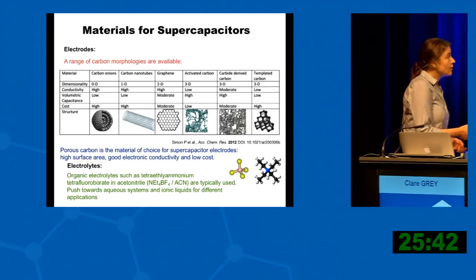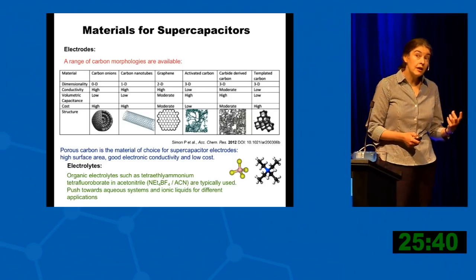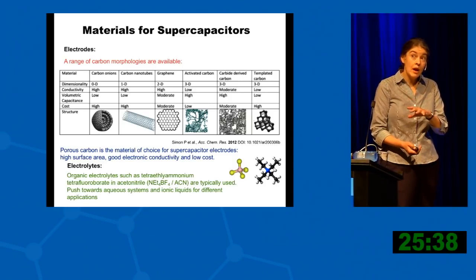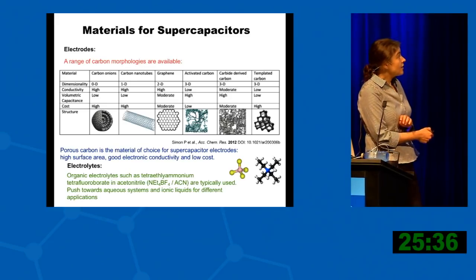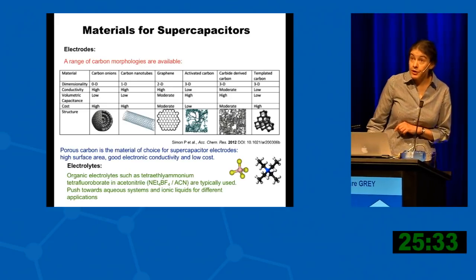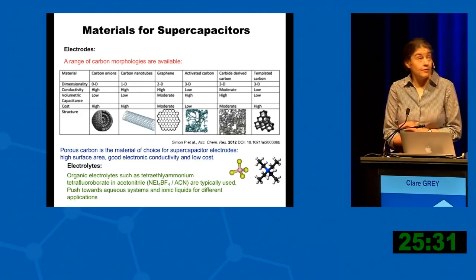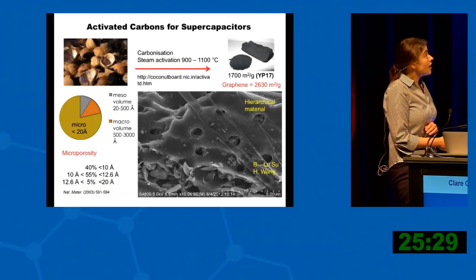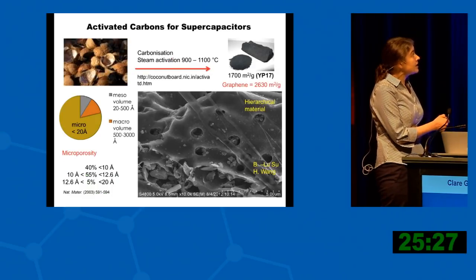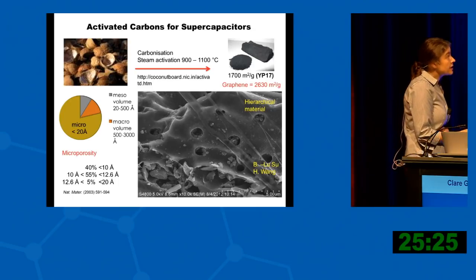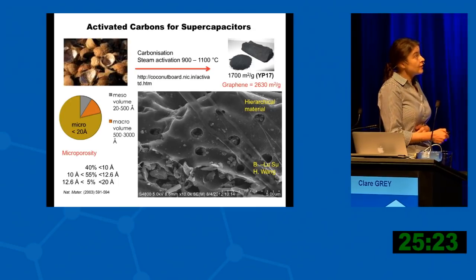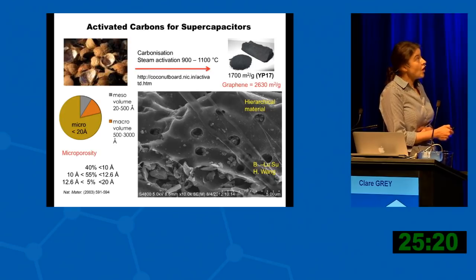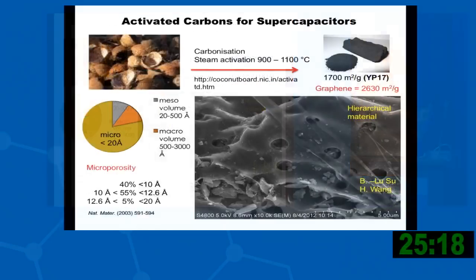As we move forward, there's a lot of work to push towards ionic liquids, because that allows the voltage range to increase. And then if you're interested in cost, then you would use an aqueous system, but then you reduce the voltage window. So what do these carbons look like? So you basically take a coconut, you steam it and activate it, and you make these beautiful hierarchical structures where you can see the holes that have come from the original lignins of the materials and also from the bubbles as you activate these systems. And they have very, very high surface areas.